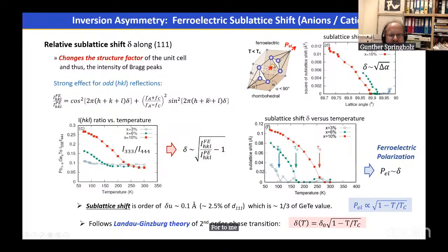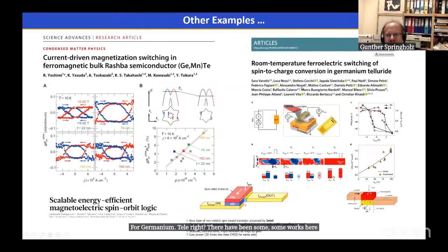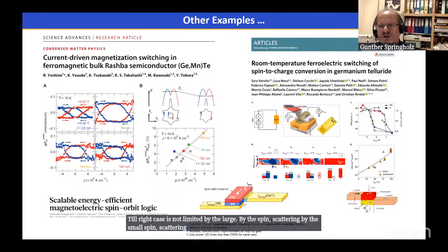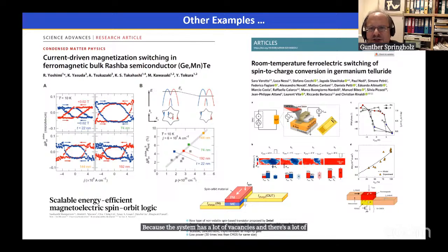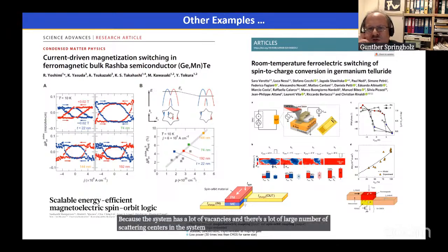For germanium telluride, there have been some works shown here, just copied from the literature. There's a group in Milano, Christian Rinaldi and Riccardo Bertacco, that have made this device and demonstrated ferroelectric switching in these devices, and they give a rough estimate of the spin to charge conversion efficiency. As I said, the spin conversion in the germanium telluride case is not limited by the large Rashba coupling constant, but by the small spin scattering time, because the system has a lot of vacancies and there's a large number of scattering centers in the system. For lead germanium telluride, we have not yet